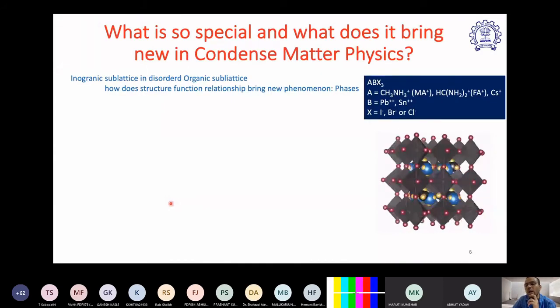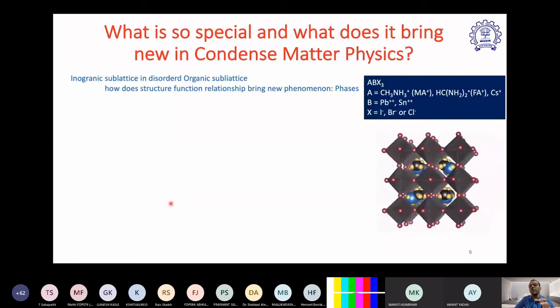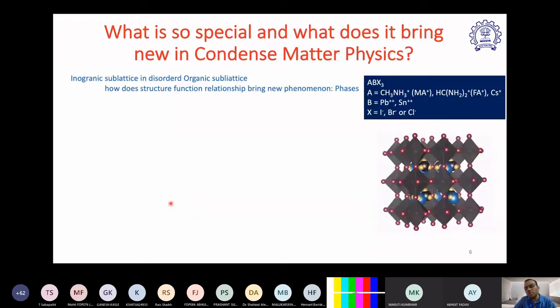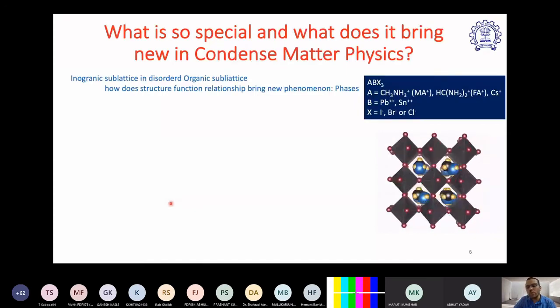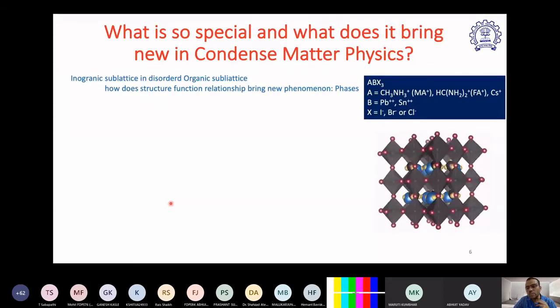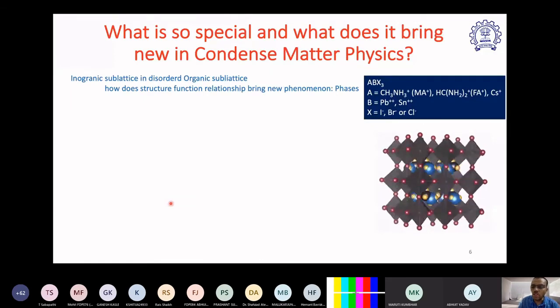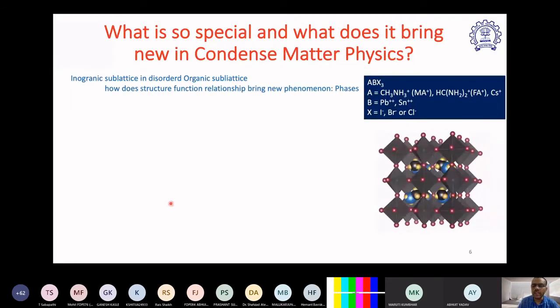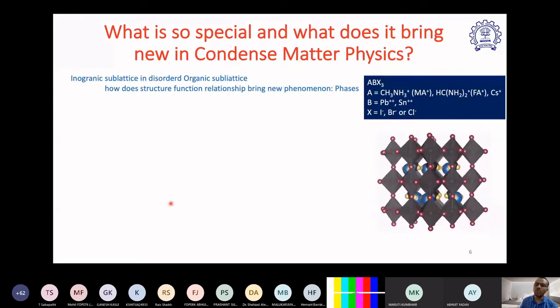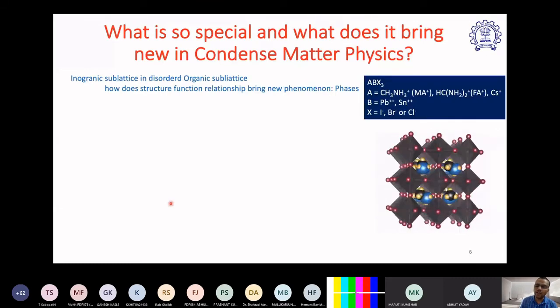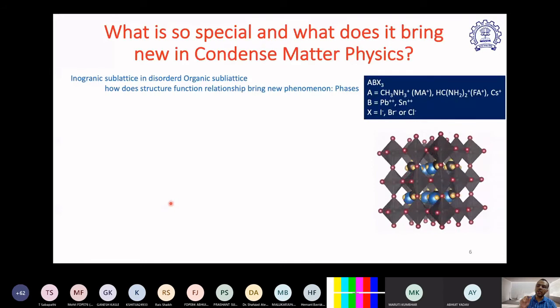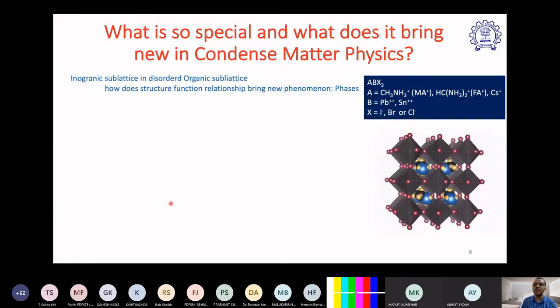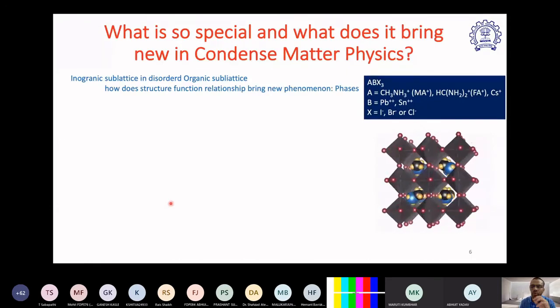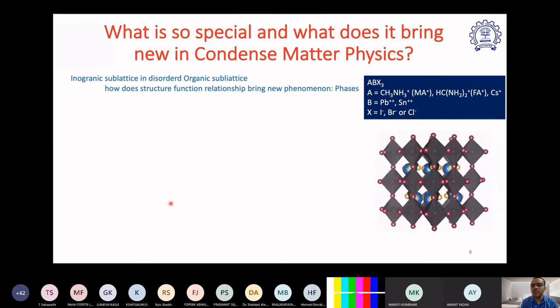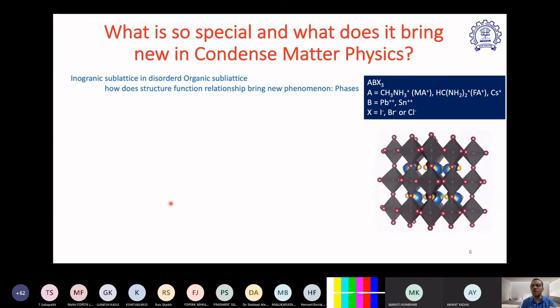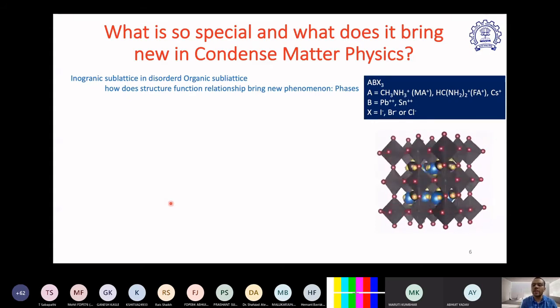So when I had methylammonium lead iodide, lead and iodine sit at the bottom of the periodic table. If I replace my iodine with bromine, what will happen? The ionic radius of bromine is smaller than iodine. Then my octahedra, these gray balloons, will become small, and this methylammonium organic cation will feel more squeezed. Further, if I remove bromine and put chlorine, these gray balloons will become even smaller, and I will have lead chloride, which has a very small balloon compared to iodine. Then this organic cation, which is sitting in the opening space of this lead PbX6 cage, will feel further squeezed. The freedom of movement of this methylammonium organic cation will get much more restricted.